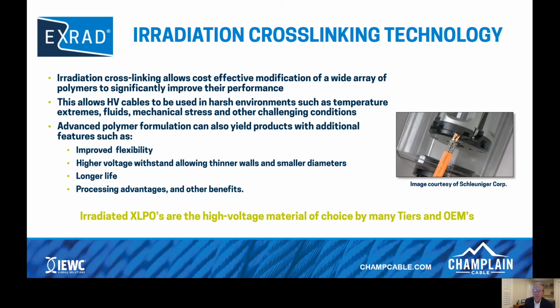And there's also processing advantages, and this shouldn't be dismissed. The processing of the cables is very important to the tiers. They are cutting and stripping cables hundreds of times an hour, sometimes thousands of times an hour. And the cables need to cut and strip cleanly. And irradiated XLPOs generally do that quite well, and some chemical cross-linking methods do not do that as well. So the takeaway from the irradiation portion, I think, would be that irradiated XLPOs are becoming the high voltage material of choice by many tiers and OEMs.